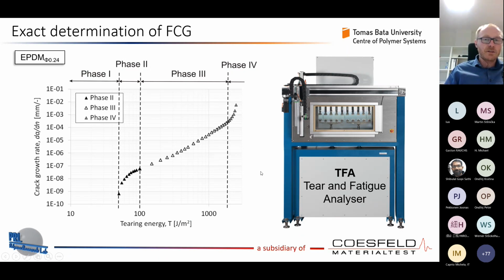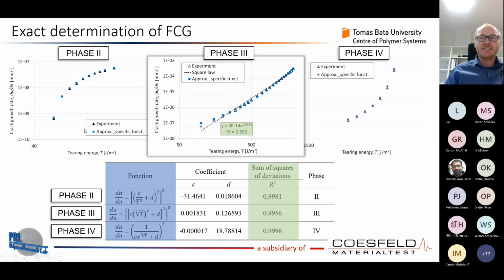We performed all the phases, and now there is a detail of these three phases. Of course, we avoid the first phase and start with the second one, starting with T0. This is this diagram. Then in the middle we have the stable crack growth, the parallel phase, and the last one is close to TC, up to TC, of course. What we can see here with the black points are the experiments, and with the blue points an approximation with a specific function defined from our side for each region. That means we define, and you can see it here in the blue rectangle, three different specific functions, one for each phase.